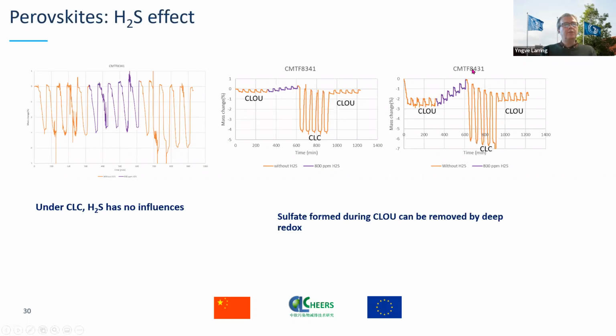For the CMTF 8431, it seems to be a little bit more critical. This one also has a little bit more change in microstructure, giving high surface areas and more sulfur absorption. But you see, this one also can be regained after with some deeper redox, which is also the case of the CHEERS project, where we do deeper redox rather than in the normal CLC type system we use at other places.